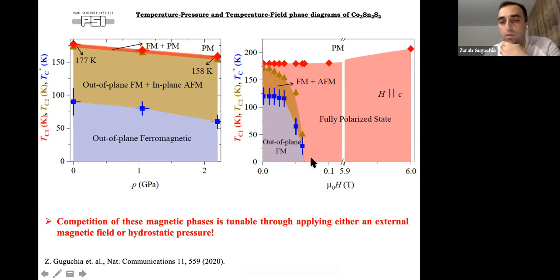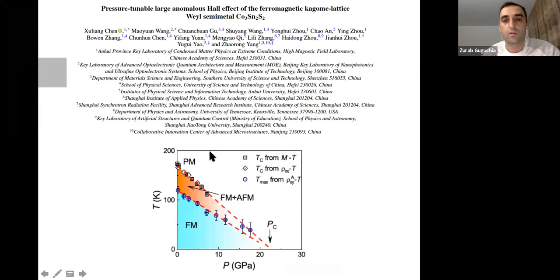So a much stronger effect was by magnetic field. Less than 0.1 Tesla is enough to fully polarize the spin along the C direction. Later on, there was a group from China who extended the pressure studies up to 20 GPa, and they have shown that this ferromagnet plus antiferromagnetic state is stable up to like 20 GPa. And the ferromagnetic also stays stable up to 20 GPa.